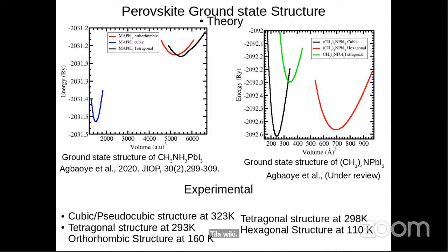Recently, we also attempted the same thing for tetramethyl ammonium lead iodide to see what value we can get from it. Methyl ammonium lead iodide has been worked on extensively, and it has been able to generate experimental efficiency which could rival that of silicon. But here we want to see what we can get from tetramethyl ammonium lead iodide. Some of the demerits of methyl ammonium lead iodide are that it has stability issues, and the lead could be toxic, and a handful of other issues.